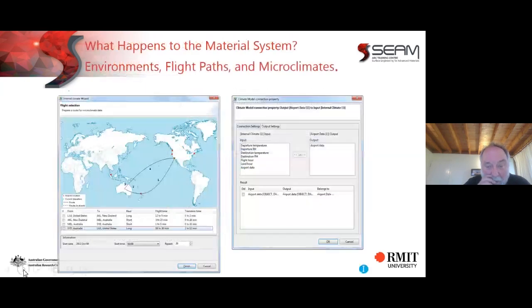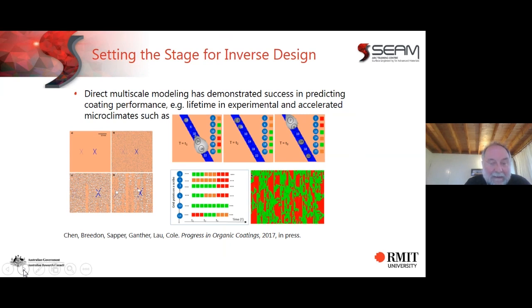As we mentioned before, we can design a flight path to know where the aircraft is, or alternatively, we can look at a test. Test is a salt spray test. These little diagrams show how water is forming down the surface, and so we can find out what the microclimate is. In this case, we're simulating a scribe in a paint film in a neutral salt spray test, and we're looking at where the droplets are.